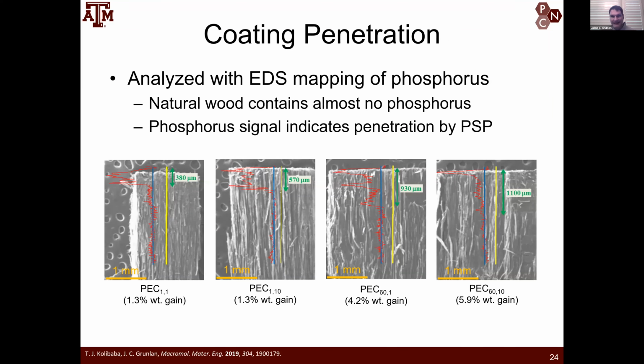And so we can look with EDS to see how deep that polyelectrolyte complex coating went into the wood. And it looks like in the best coating, it went about 1 millimeter deep. So we didn't even need to fully coat all the wood. Just the surface 1 millimeter of the wood provided tremendous flame retardancy.